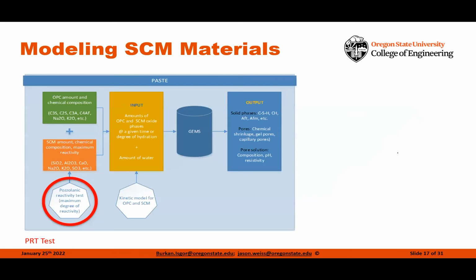So how do we start to integrate this and bring this all together? Well, the modeling approach that we're using here is we can actually take the chemistry of the OPC and bring that into the picture. And again, we have a pretty robust database where we've got all of the North American cements that we could find. They're placed in the database and we have that information. We can actually add limestone into the system if we want as well. But now we can also add supplementary cementitious materials.